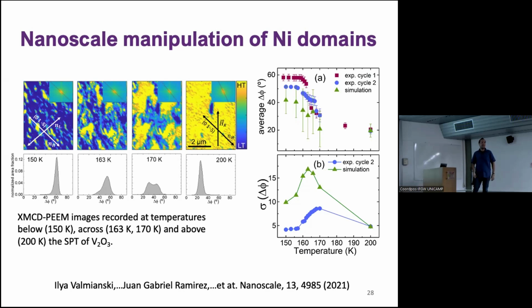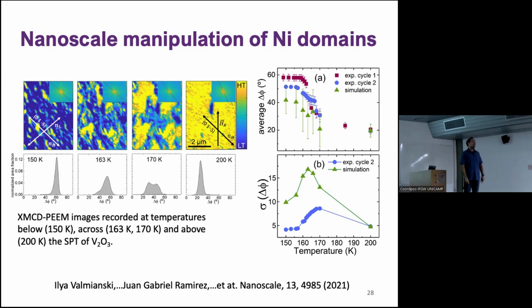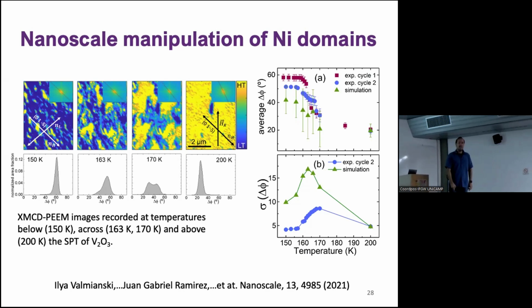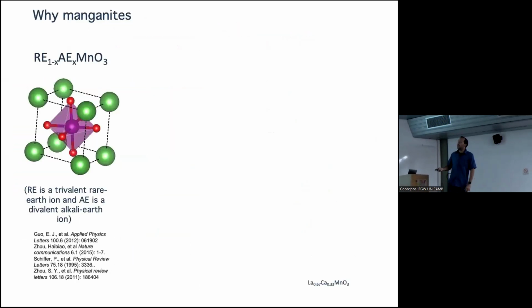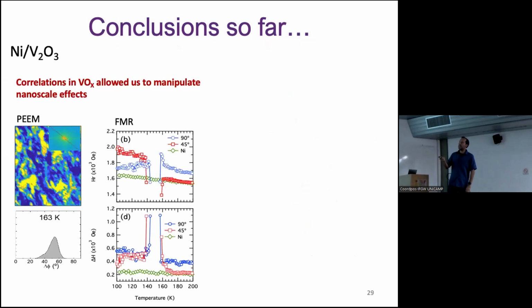These domains are very tiny and they are not expected to be in a nickel film. If you take a nickel film and measure how big the domains are, they are huge, they are microns. And these are nanometer scale magnetic domains. So in a way, we are basically controlling effects at the nanoscale by using the correlations in these oxides. That's the message here, okay?